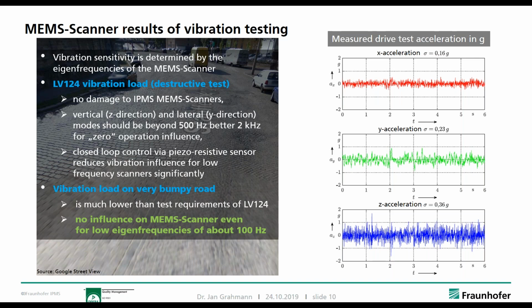So that means for LiDAR application, first of all, we can go to quite large mirror apertures, because usually a larger mirror aperture means the spring has to be a bit softer, or the whole eigenfrequency becomes lower because of the larger mass. And secondly, we can go to quite large deflection angles so that we can well achieve 60 degrees field of view for a 5mm scanner, which could be quite interesting parameters for a LiDAR application.